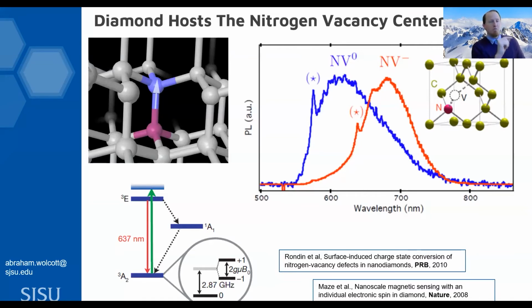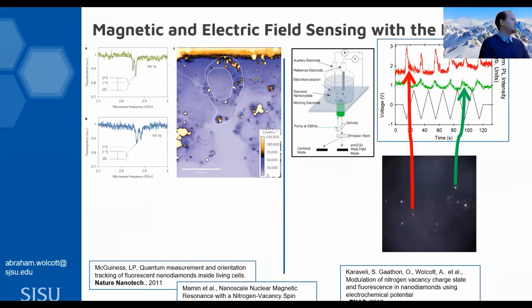And of course, most work has been done with oxygen-terminated diamond and hydrogenated diamond. For oxygen-terminated diamond, typically you have more of a NV- charge state probability. And then if you hydrogenate the diamond surface, you're more likely to have NV0 properties. What I think would be interesting is to tune the surface properties to allow that switching to happen very, very quickly, so you could develop a more sensitive electric field sensor.